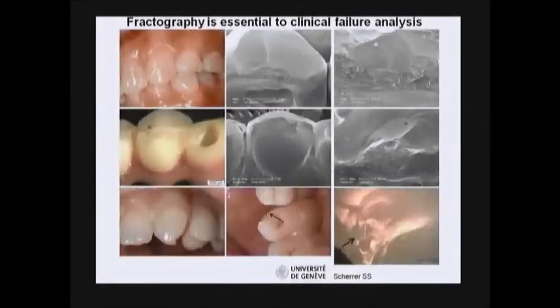And the clinics, here's the clinics, and if you want to see chipping, you just have to ask Susanne Scherrer. She's going to provide you all the images that you need. However, I must admit, my chippings are mainly related to wear. I always see wear on the surface. This is an implant case. I don't remember if it chipped off after 6 months or less than a year, any case. Huge chipping. But if you look closely, there is a lot of occlusal wear going on. These patients that have just implants all over the place, they have no perception anymore of their biting force. And believe me, they go powerful on it. And they grind, they wear it off.